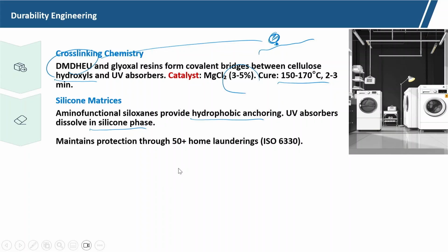It maintains protection through 50 plus home laundering as per ISO 6330. So, after more than 50 home launderings, it maintains the protection.